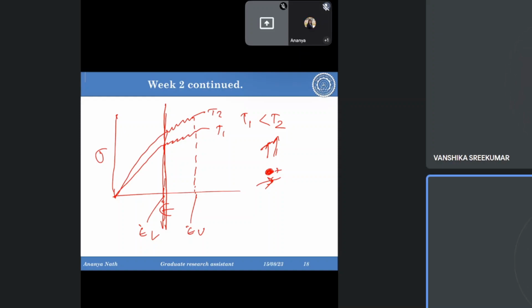No, no. The dislocation mobility will be higher in this range, right? In this range, the mobility of the dislocation is higher than the solute atoms. But when they enter this region, it will be opposite. The dislocations will not get enough time to move, and the solute atoms can always move, because they just need to find a vacancy and move. They will move and be seated in front of the dislocations until this point.